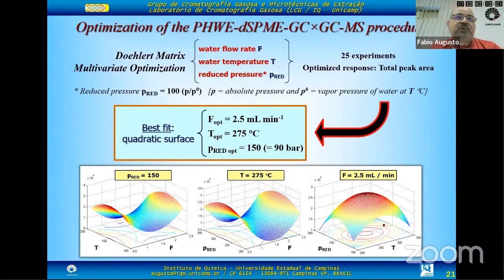To optimize the extraction conditions, we use multivariate procedures. Everything we do in our lab is optimized through multivariate chemometric strategies because there are too many variables to optimize, especially in microextraction techniques. It's almost impossible to determine the optimum conditions using univariate procedures, optimizing one condition at a time. So we have to use those multivariate approaches. It's much more intelligent. We optimize the water flow rate, the water temperature, and the pressure of the system in terms of reduced pressure, not absolute pressure. Reduced pressure is the relationship between the pressure and the vapor pressure of water at the temperature of that particular experiment, using a multivariate approach called Doehlert matrix optimization.